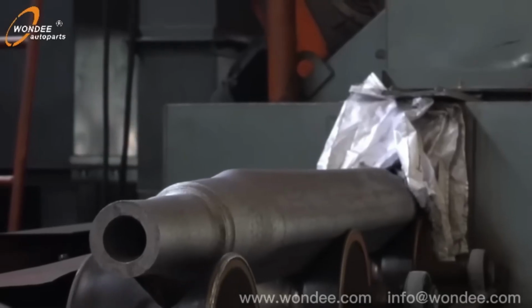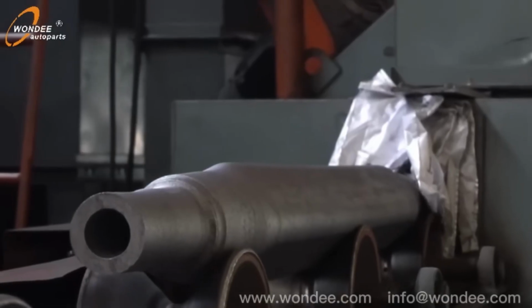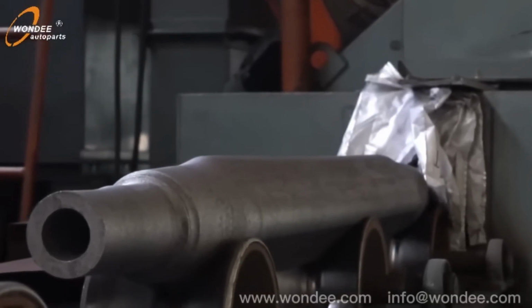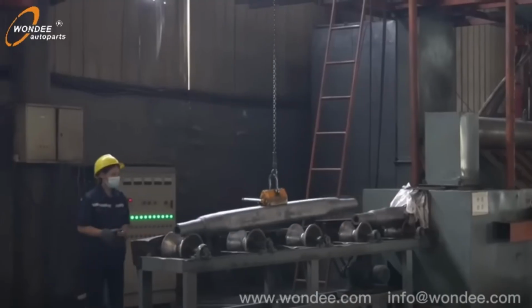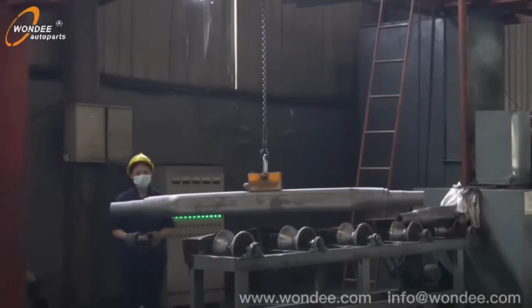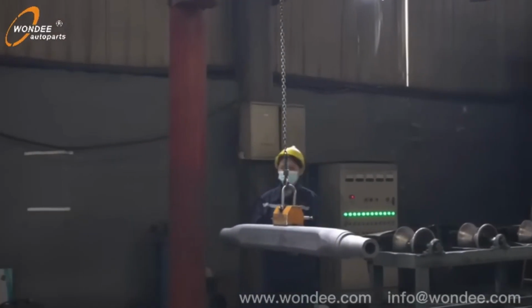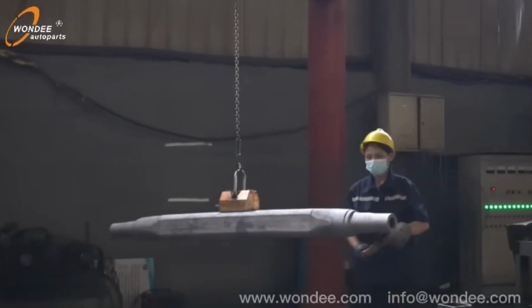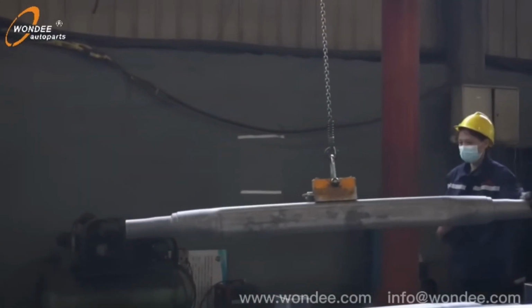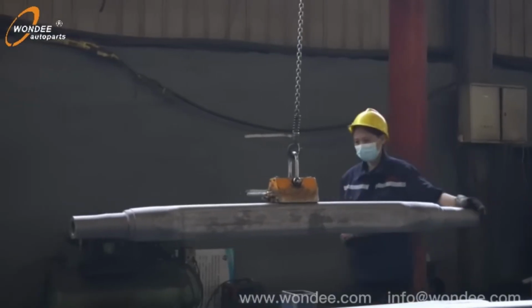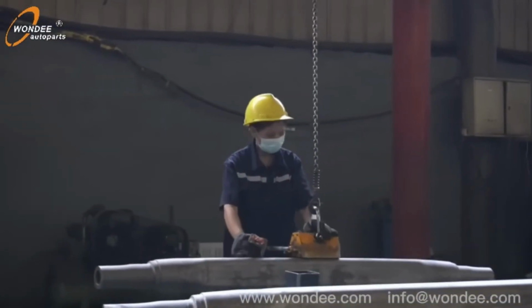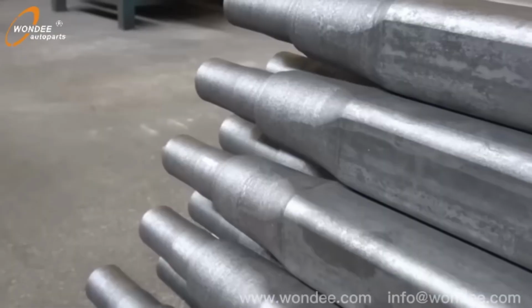Additionally, shot blasting induces compressive stresses on the axle surface, improving fatigue strength and resistance to cracking under dynamic loads. Thorough coverage is crucial to avoid untreated spots that could compromise corrosion protection or coating quality. After blasting, axles are inspected for surface cleanliness and finish, ensuring readiness for subsequent machining, painting, or coating processes.